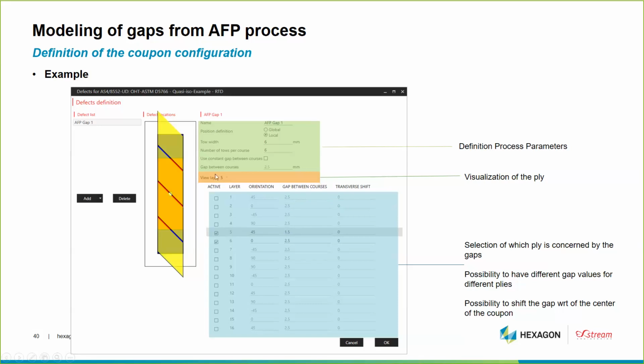This is what we visualize here. I have a view to see layer 5. Layer 5 is oriented at 45, that's what we see here, and we want a gap between the courses of 1.5 millimeters. So we can select the ply that is concerned by the gap, and we can have different gap values for different plies. And then we can also shift, or translate, the gap with respect to the center of the coupon.